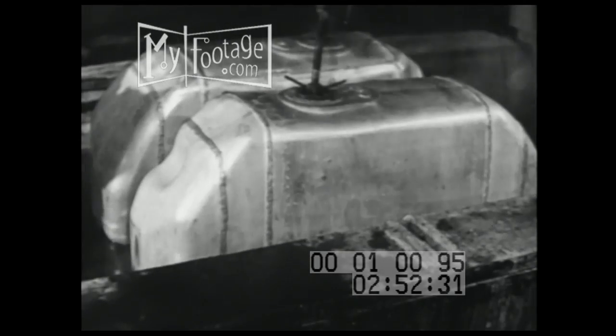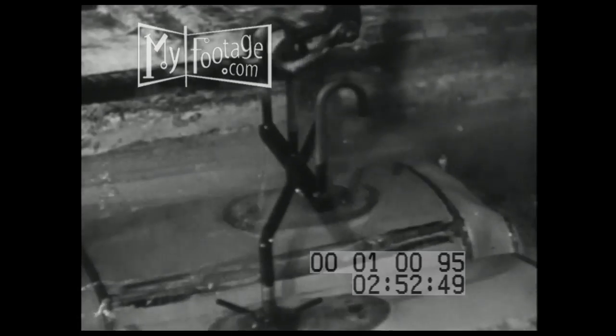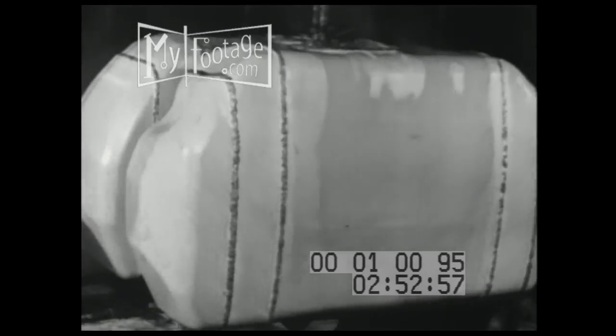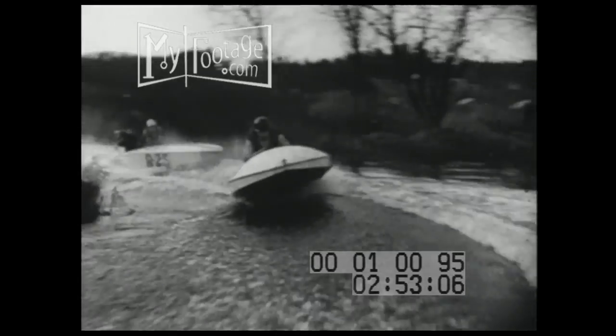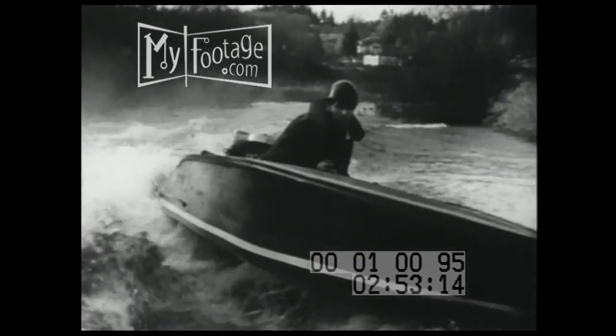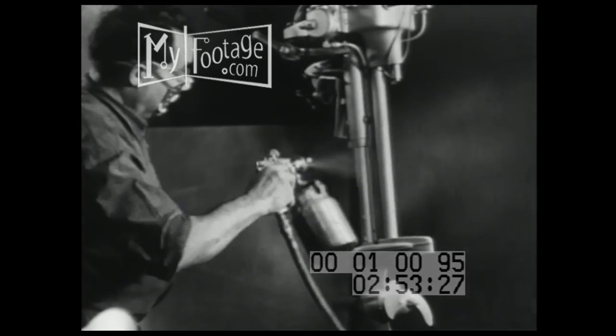By chemical means, an oxide film is applied which is thicker than the natural film and gives greater protection. In one of the Alrock processes, an alkaline chromate solution is used to oxidize the surface, and a second chemical treatment seals the oxide coating. Alrock coatings are used for both protective and decorative purposes. These gasoline tanks are given an Alrock coating to protect them from the corrosive effects of aviation fuel. On outboard motors, exposed parts get better protection — the Alrock coating bonds the paint to the metal and adds to the protection afforded by the paint.